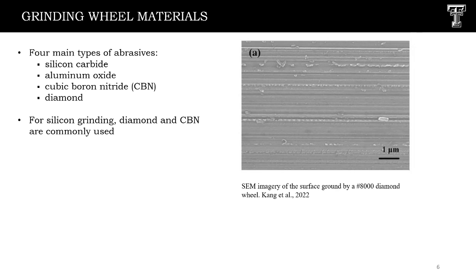There are four main types of abrasives used in grinding. We have silicon carbide, aluminum oxide, cubic boron nitride, most times called CBN for short, and diamond, of course. For silicon wafer grinding, diamond and CBN are preferred because of their high wear resistance and thermal conductivity. To my right, you would see an image that illustrates the surface quality achievable with an 8,000 diamond wheel.